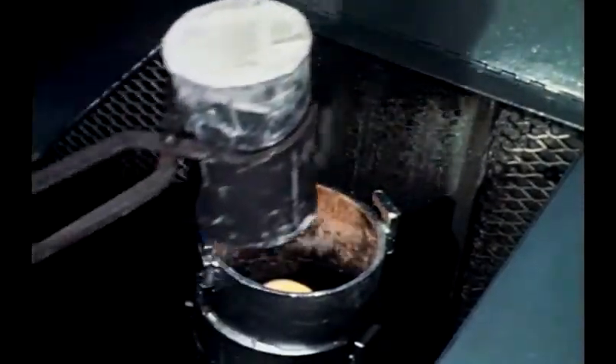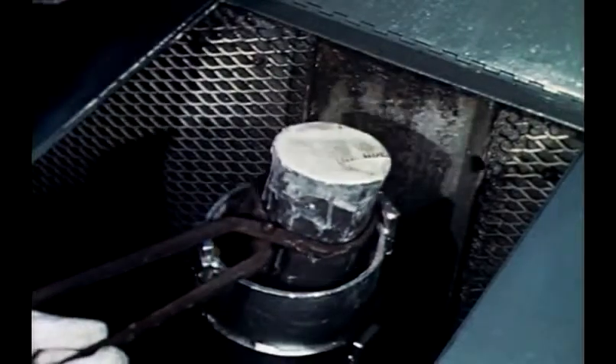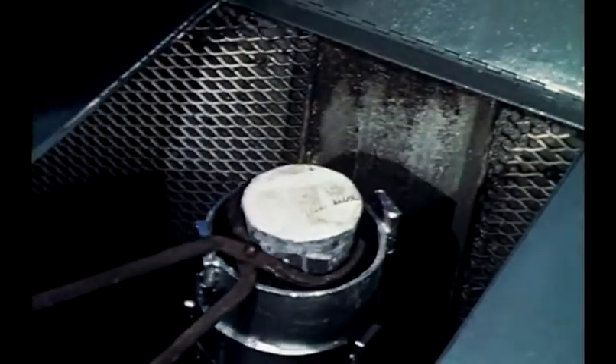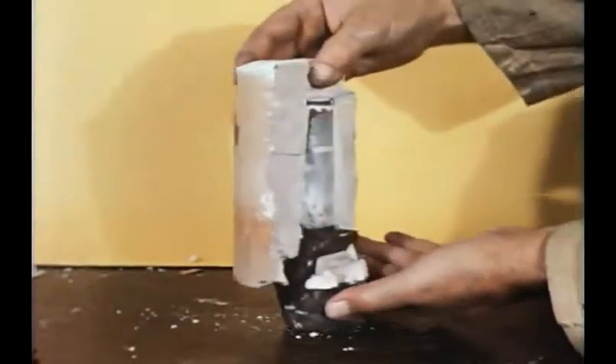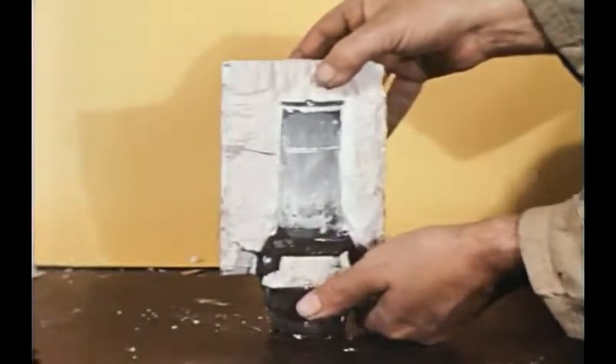Metal alloy for the casting is melted in an electric induction furnace. When the metal reaches a temperature of 3000 degrees Fahrenheit, the crucible of molten metal is placed in a centrifugal casting machine, and the hot mold is placed over it. As the casting machine is spun, the molten metal is thrown into the mold. The casting is removed by breaking away the mold.